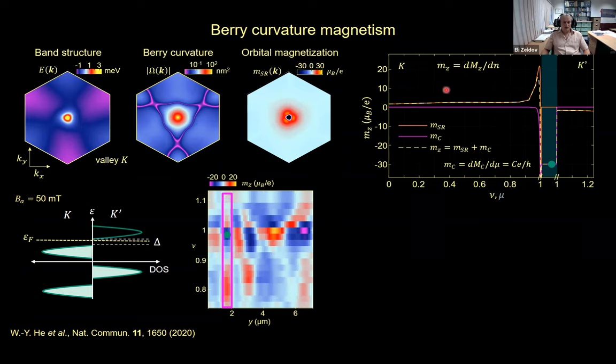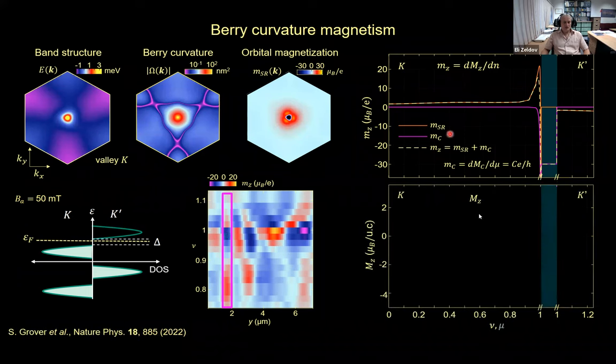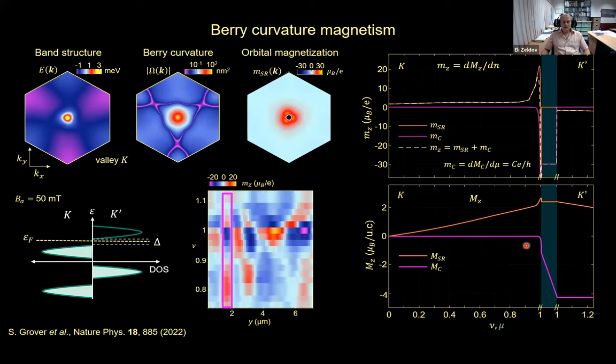For this, rather than looking at the differential magnetization, we should look at the total magnetization, the integral of this. The integral of the self-rotation magnetization increases gradually as we move towards the top of the band. It has this overshoot here and remains constant in the gap because there are no density of states there. Whereas the Chern magnetization is zero in the metallic state and it increases in magnitude linearly in the gap as a function of chemical potential,